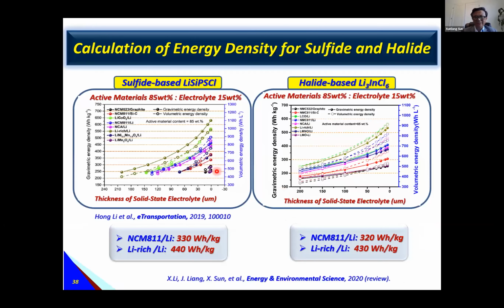So talk about the energy density, if we talk about the system compared with the sulfide. Here the Honli group recently made a comparison with different cathodes. What they found is that if the solid-state electrolyte thickness is 50 micrometers combined with 811 and lithium metal, they can reach an energy density of 330. If you combine lithium-rich, they can get 440. If we compare, just using lithium-indium chloride gets a similar number, for example, with the 811 or lithium-rich.